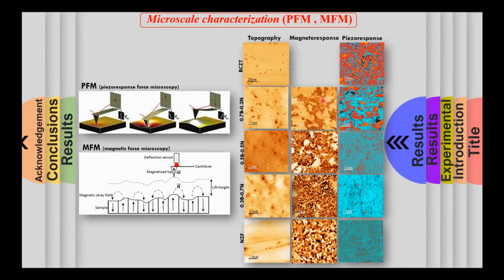It is also observed that as we keep on increasing the weight fraction of nickel zinc ferrite, that is the magnetic phase, the relative area that shows the magnetic contrast also increases. In contrast to MFM, if we see the piezo response, of course, the pure BCZT showed the strongest piezo response. However, among the composites, only the composite with 70 weight percentage of BCZT showed strong piezo response. It weakened in other composites. And of course, no response was observed in the magnetic sample.